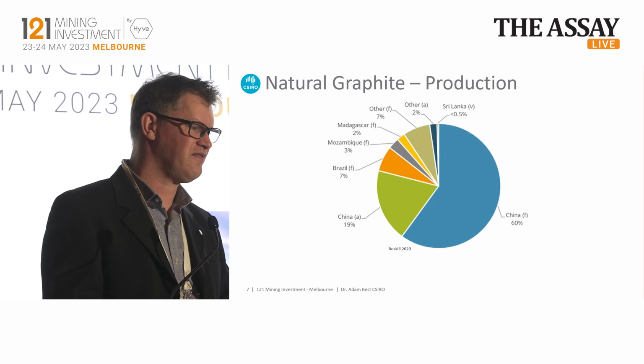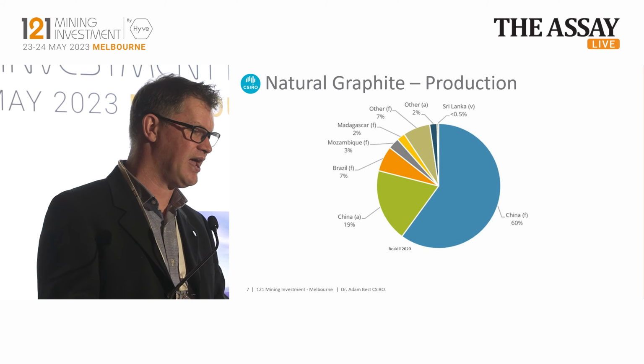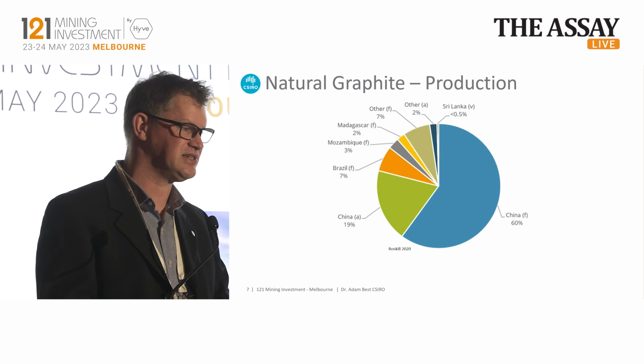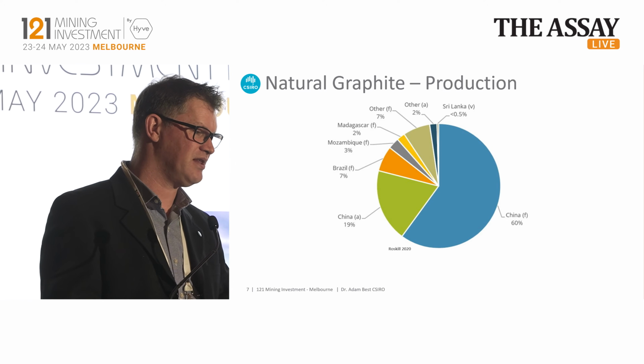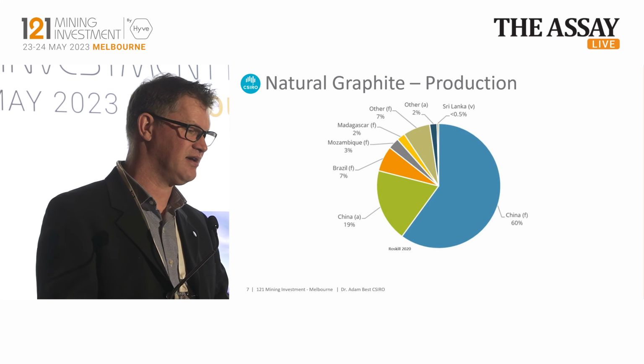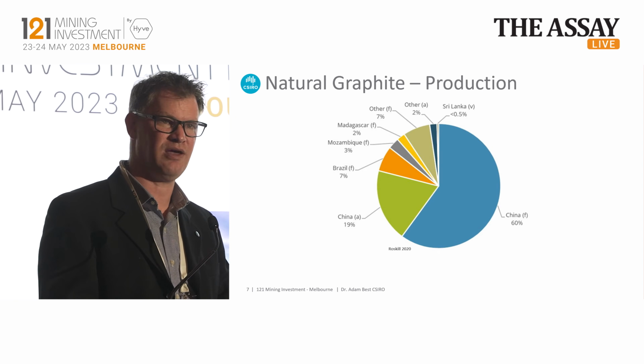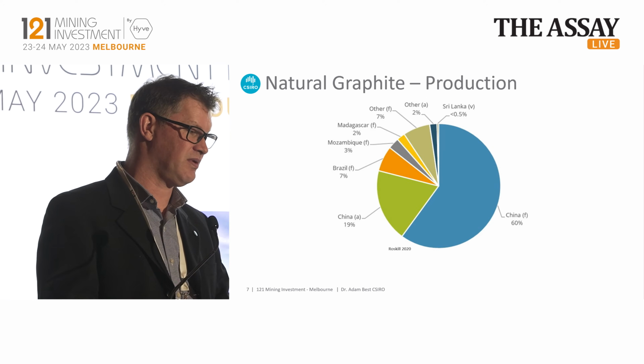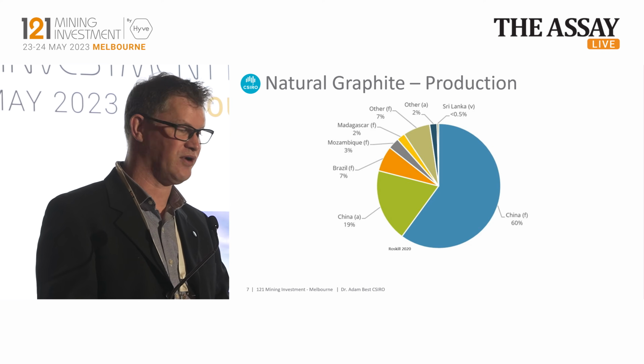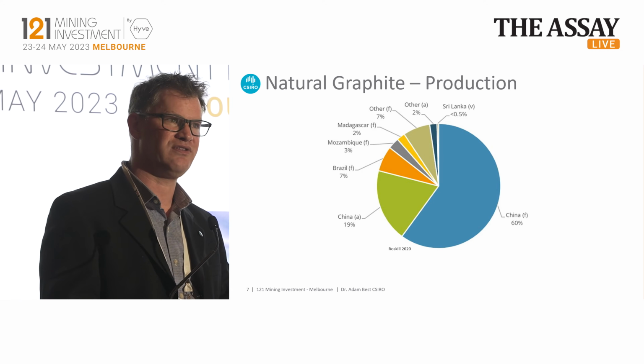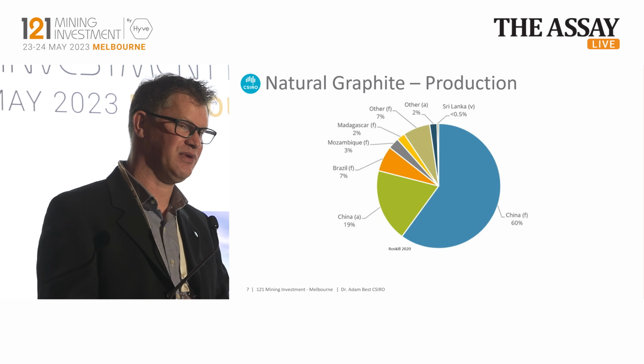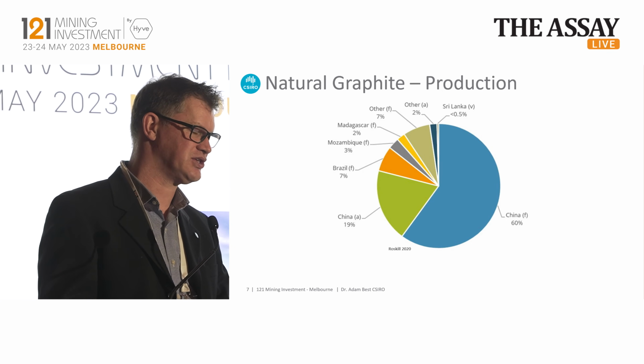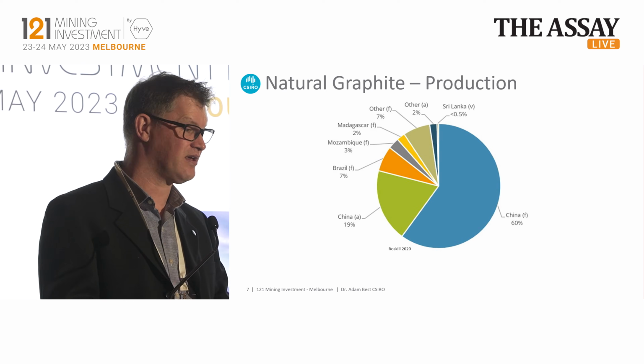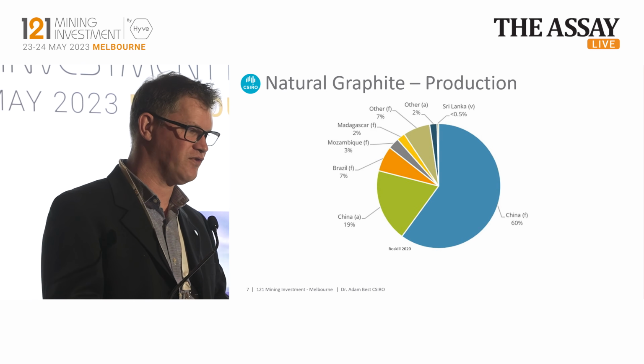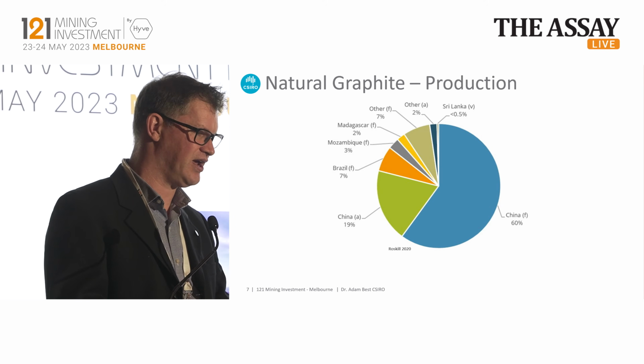So, as I mentioned earlier, graphite may be found around the world, but the dominant player in this field, and this is from 2020, this may have changed a little bit, but I wouldn't suggest too much, but China is the dominant player here in graphite. So you can see here they've got 60% of this market. The others are all small, and even we don't even rate in 2020 on that plot, as we still don't actually produce graphite material for actual battery production. So there's still quite considerable opportunity here for Australia, and particularly since there's been a very large reworking of the battery value chain as we know it.